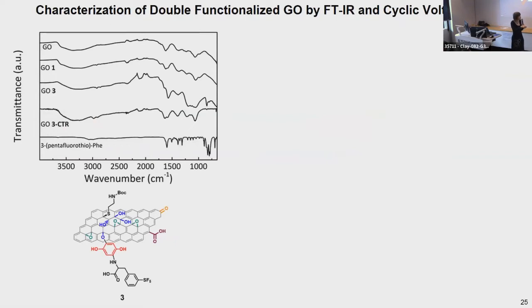And also FTIR was very useful because the S-F stretching peak is very specific and is in this area, as you can see for the FTIR spectrum of the molecule alone, the phenylalanine derivative. And we could find this peak only in the FTIR spectrum of the final conjugate.